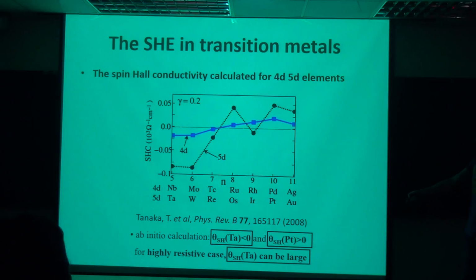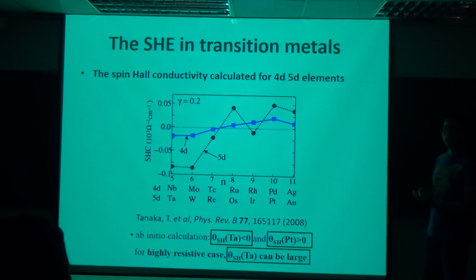And the data I showed here is from more systematic work by Tanaka and co-workers. They showed that the spin Hall angle or the spin Hall conductivity for 4d and 5d materials actually will change sign depending on which side of the periodic table the element is on. So for the left-hand side, for instance tantalum and tungsten, you'll get a negative sign. And for platinum and gold, you'll get positive signs. So that means if we want to verify that what we observe experimentally is really coming from the spin Hall effect, just check the sign first.